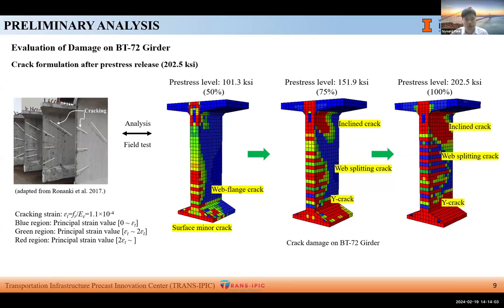Bottom flange was almost fully cracked in end region where horizontal pre-stressing strands are running through and web splitting cracks also developed. At the end face with pre-stress of 202.5 KSI, the web region was cracked more than 50% with vivid cracking pattern of inclined, web splitting, and Y shape. Although this numerical model followed the AASHTO guideline, we can still see that end region cracking can be a problem. Also, by comparing to the field test, although the model is not the same, the cracking pattern was similar, verifying the numerical model.